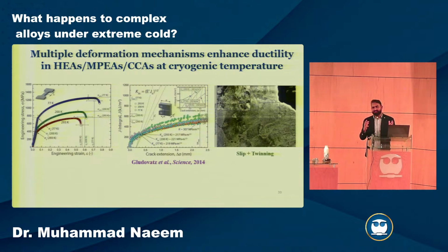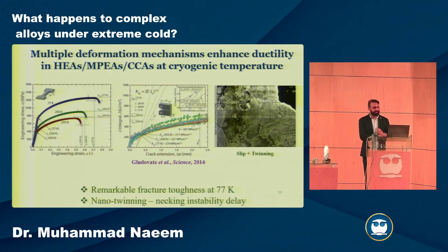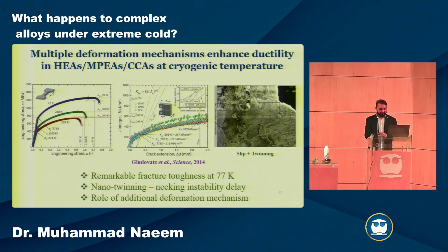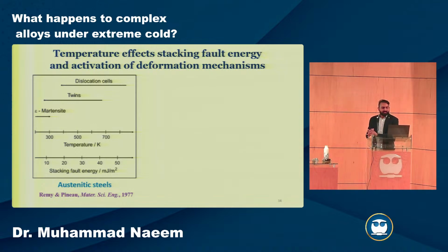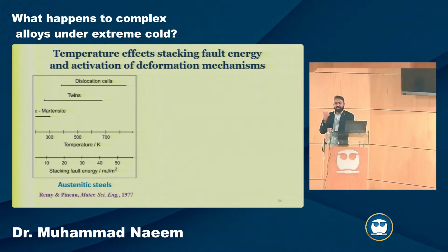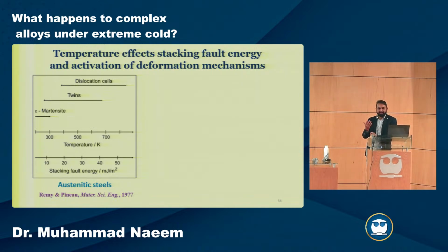So these two mechanisms ultimately contributed to better mechanical properties. All right, so I already mentioned that. Now, how these mechanisms change depends on something called stacking fault energy, which is material dependent, but it also depends up to a certain extent on temperature if you have the same material. So this is for austenitic steels, for example.